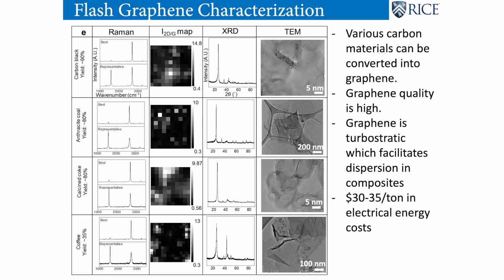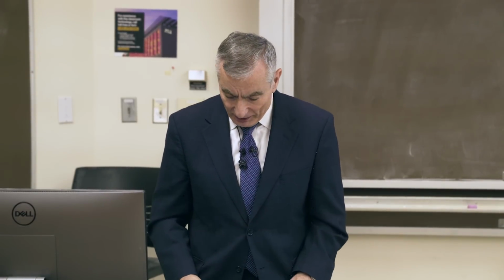And so you can see you can do it with carbon black as your source, anthracite coal, calcined coke, or you can do it with coffee. Coffee is a carbohydrate, C6H12O6, so it's 40% carbon by weight. We can get 35% yield of graphene from waste food, waste plastic, whatever is made out of carbon. Most of the things you see around you, if it's not glass and it's not metal, it's carbon, including us. And you can turn all of these things into graphene this way.